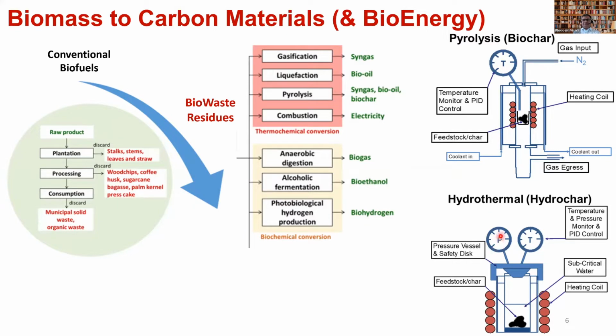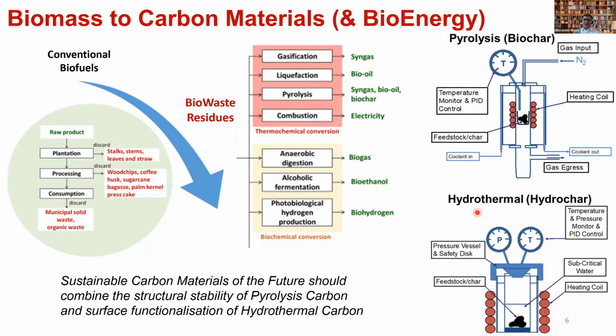Another method that is even more sustainable is hydrothermal carbon, in which we take the same kind of feedstocks, suspend them in water, and take the temperatures only to 200 to 250 degrees Celsius. This is called hydrothermal conversion. They both have different advantages. One advantage of the pyrolysis carbon is that it has strong structural integrity, but it is not always as well functionalized as one would want it to be. On the other hand, the HTC material, that is hydrothermal carbon, is highly functional, but it does not have as strong structural integrity. So sustainable carbon materials of the future should combine the structural stability of pyrolysis carbon and the surface functionalization of hydrothermal carbon. If we can achieve that, then we have a stellar material going forward.